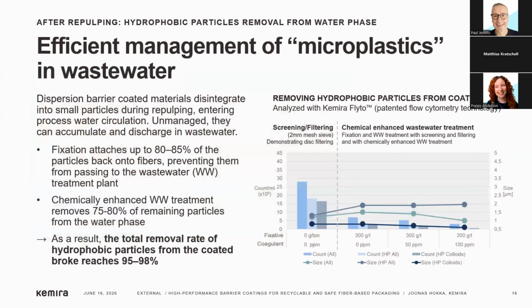So let's look now at what happens in the water phase. As we saw, dispersion coatings disintegrate during repulping. They form fine hydrophobic particles that enter the process water. The challenge is, if not properly managed, small particles could accumulate over time, affect water quality, and impact process stability by interfering with retention and dewatering and increasing risk of deposits.